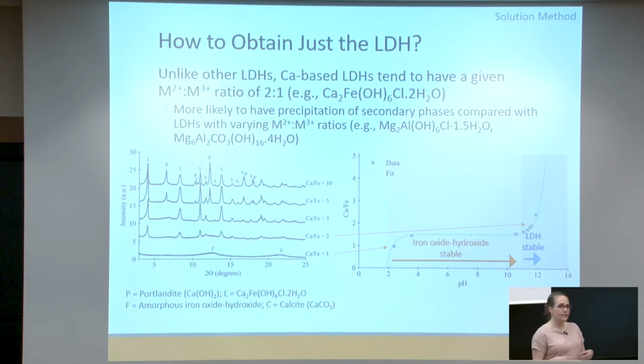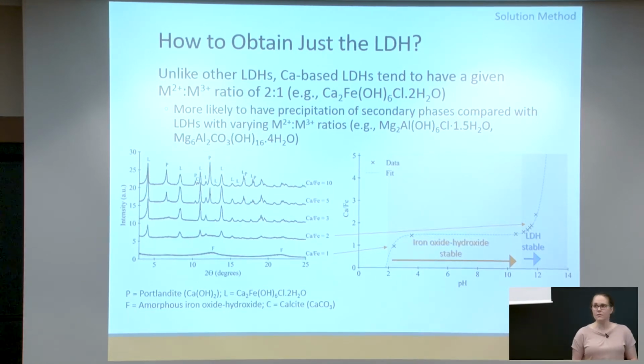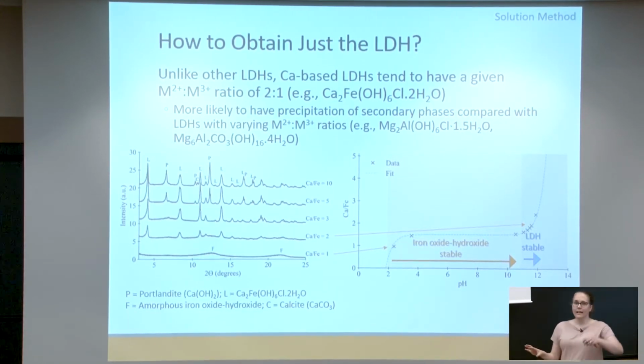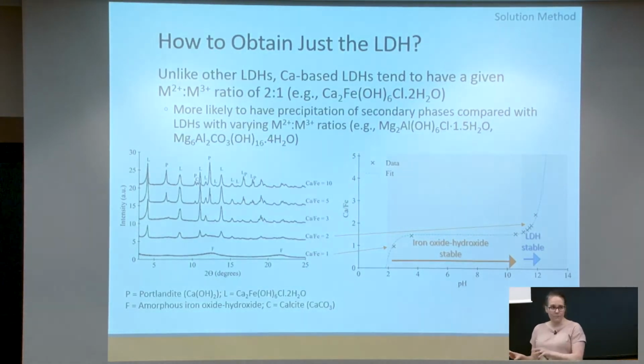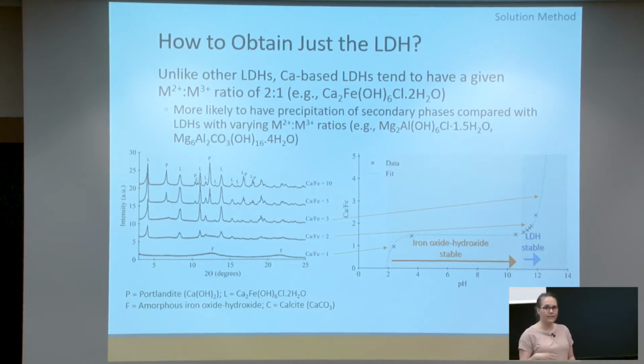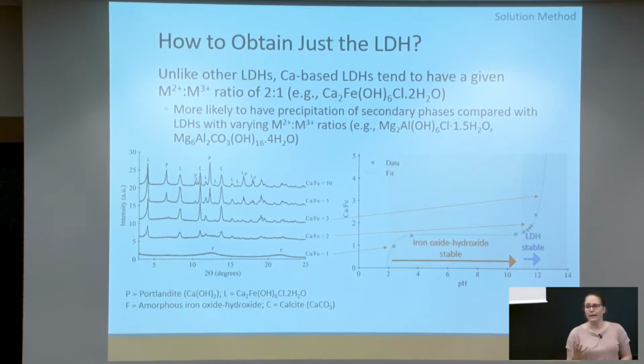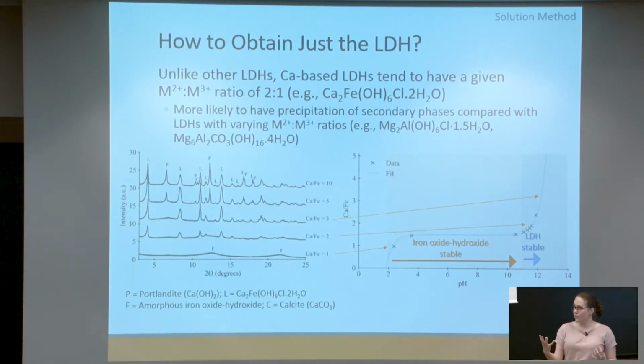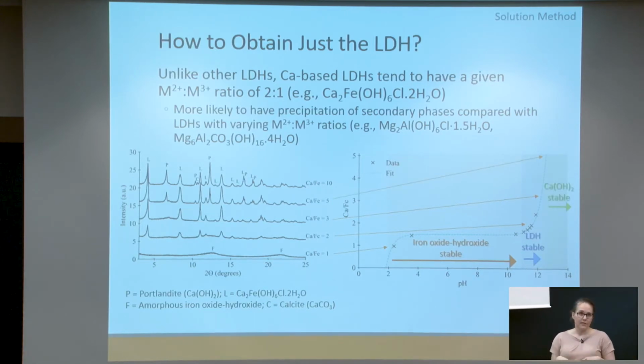And that's because the layered double hydroxide has some solubility to it, so some calcium remains in solution, and there's excess iron, and that iron forms that amorphous solid. At the ratio of 3, now we've given the system enough calcium so that there's no excess iron in the solution. So this is around the ratio that we want to be, and we have some calculations that have the exact ratio that we need to use to get the phase purity. And likewise, if you go to higher amounts, you've got even more calcium in the solution, and your pH is so high that you've formed this calcium hydroxide phase.